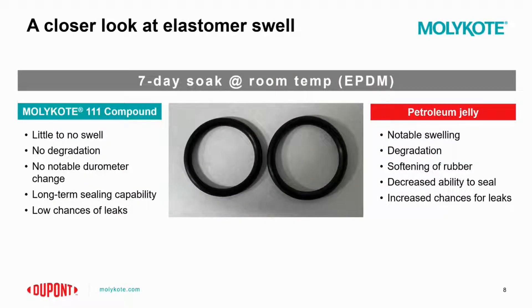Here's a visual test I conducted so you can see how elastomer swell takes place. These are two EPDM O-rings, both soaked for seven days at room temperature. The one on the left was soaked in Molykote 111 compound, and the one on the right in a typical petroleum jelly substance. The O-ring on the left showed little to no swell, no deterioration, and no notable durometer change — indicating long-term sealing capability and a very low chance of leaks. The petroleum jelly O-ring showed noticeable swelling, degradation, and softening, leading to a decreased ability to seal and an increased chance for leaks.